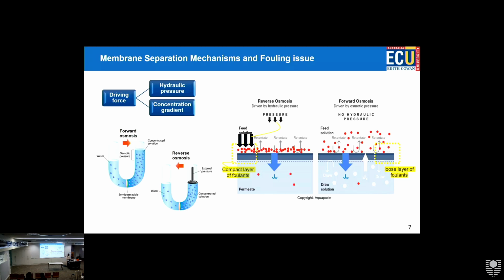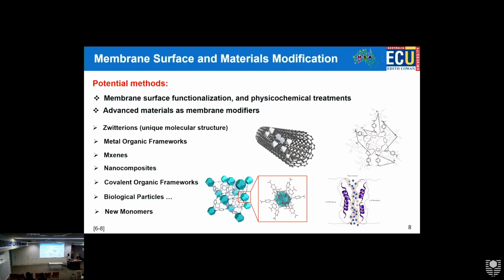So in forward osmosis we have a looser layer because we don't apply any pressure. So we have less fouling and a cheaper process, basically. What we did in our group is we started with forward osmosis because it has more potential to be integrated after the current filtration processes as an additional process. But what we want to do with those systems is to improve their efficiency. So how do we improve their efficiency? We change the membrane surface functionalities to make them more water loving, so more water permeates through them, and make them more resistant to fouling. That is done, as I mentioned, through surface functionalization or integration of advanced materials into the membranes.